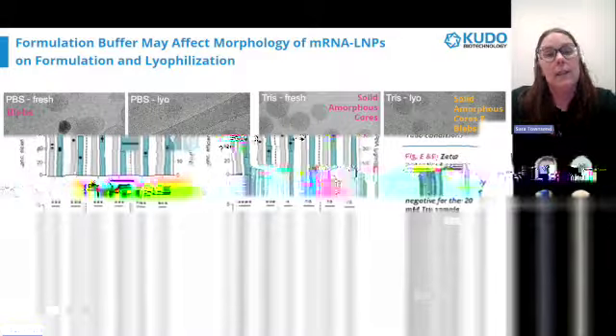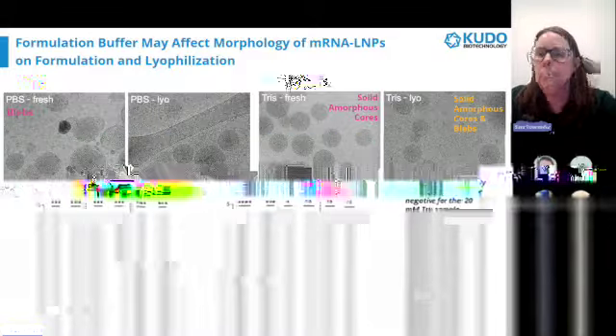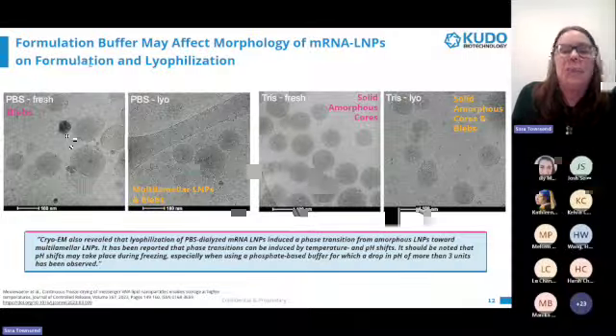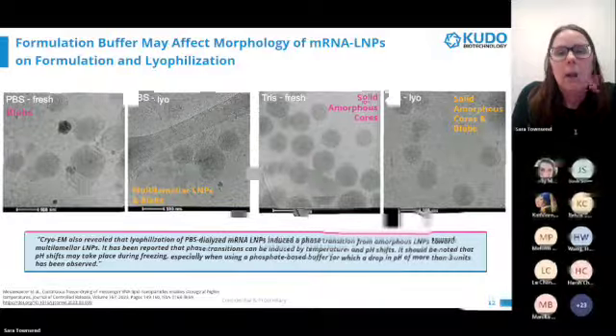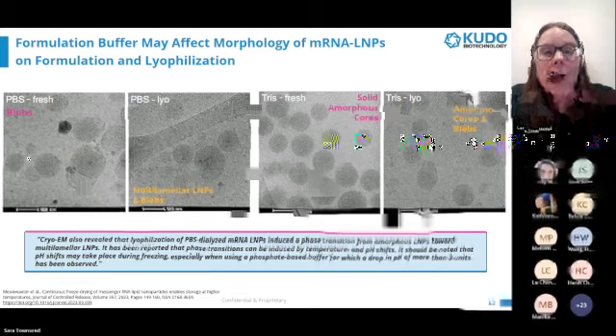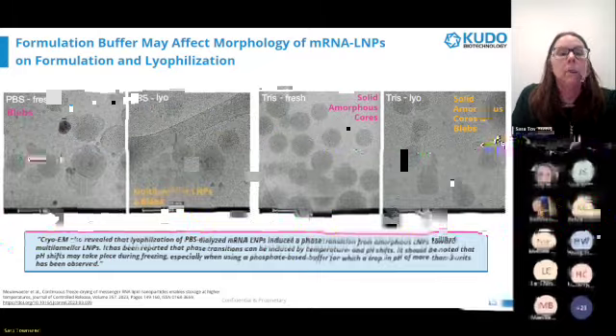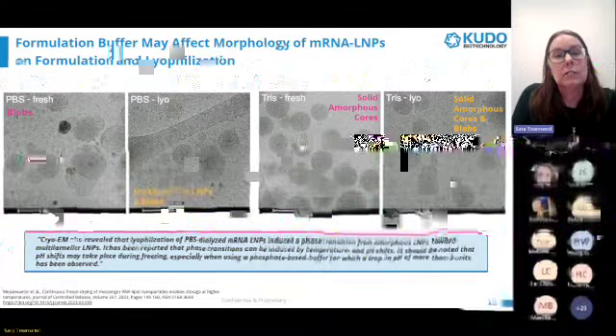In addition to the typical CQAs, they also used cryo-EM to observe the morphology of the nanoparticles before and after lyo. In fresh PBS buffer, they observe these structures here, which are called blebs. After drying, the nanoparticles change to multilamellar structures in addition to some blebs. The tris, on the other hand, initially showed what are called amorphous cores. After drying, those are present, and now blebs could also be observed.